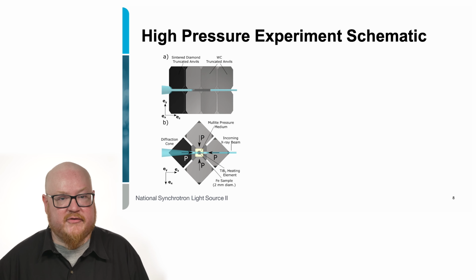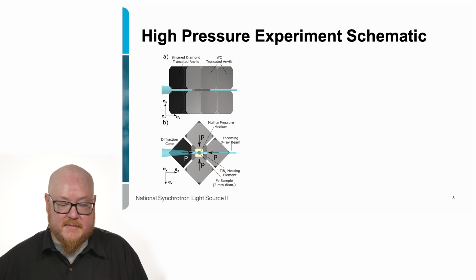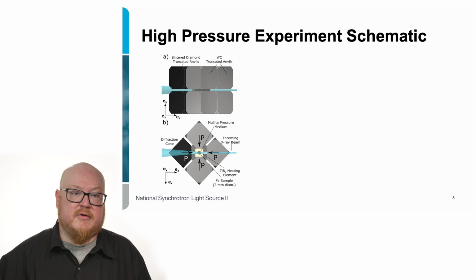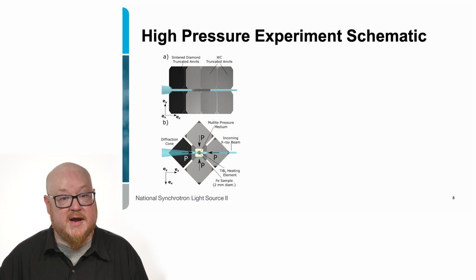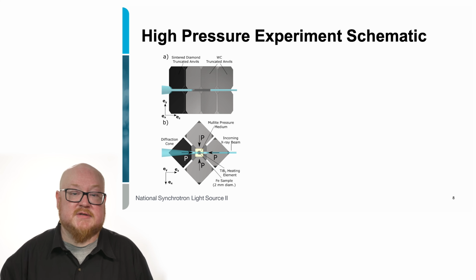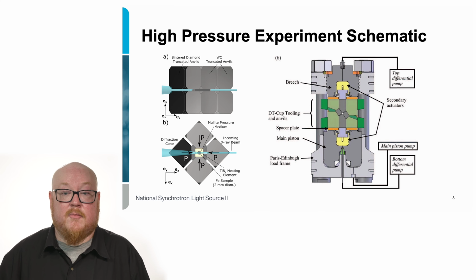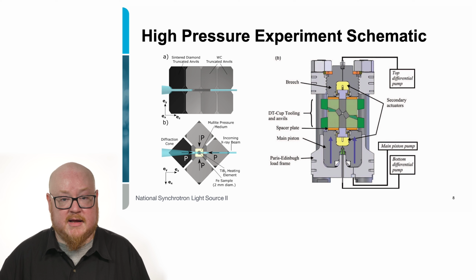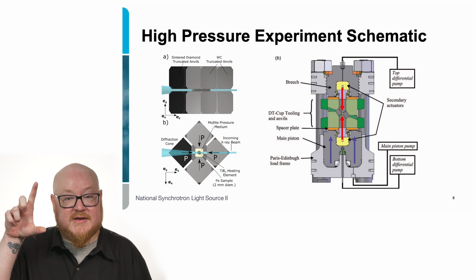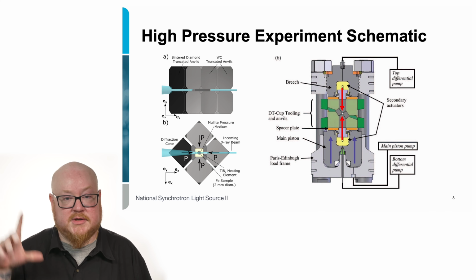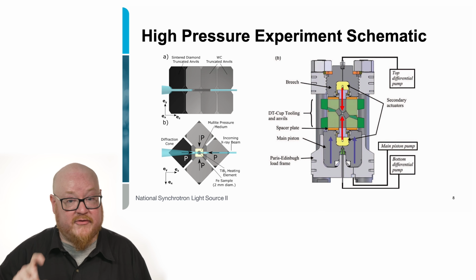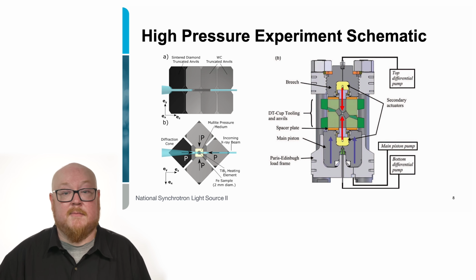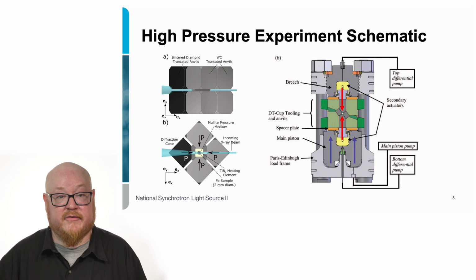And as you can see from this schematic here, the X-ray beam actually passes in between the anvils so that it can see the sample directly at every condition of pressure and temperature that we want to reach. So we then take these anvils and put them in the press, and then the press pushes up from below in order to raise the pressure on the sample. And then we have the unique ability in this design to be able to drive the top and bottom anvils separately in order to add a deformation field of strain on the sample itself. And that becomes important, particularly when we're looking at forging processes.